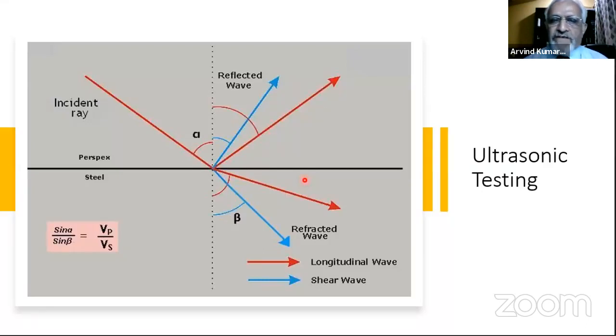Now, to understand what is 45 degrees, 60 degrees, and 70 degrees, how it is generated, I'll explain this small sketch shown here, and then you'll have an idea how the angle probes are generated. Angle beam is generated. If you see here, there is a longitudinal wave at an angle. All red is my longitudinal wave, and blue is my shear wave. Now here I have an interface. The interface I've taken is, say, plastic and steel. And in that interface I have introduced a longitudinal wave at an angle.